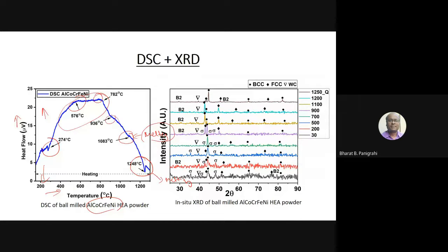And this can easily be traced by looking at the microstructure and also this X-ray diffraction. It started from room temperature and all the way it goes to 200, 500. We have taken some values, and you can see with changing temperature their diffraction profile and phases. When you move from bottom to top, you will see there is a gradual change in diffraction profiles. And whenever a gradual change in diffraction profile is happening, it does indicate that there is a slight change in the phase composition. So this is what I want to bring.